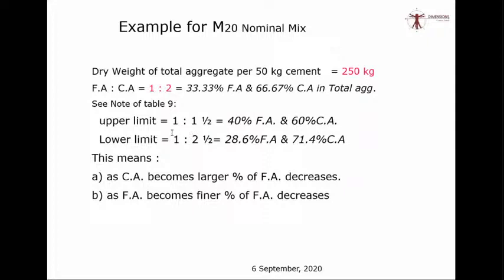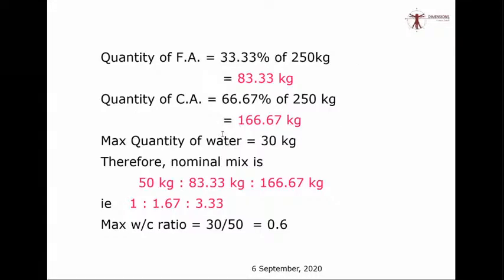See, I have taken an M20 example. The total aggregates per 50 kg of cement is 250 kg. And on a generality, if we assume that we are using 20 mm aggregate and zone 2, or it could be manufactured sand also, then the ratio between fine aggregate to coarse is 1:2, so 83.33 kg and 2 times 83.33 is 166.67 kg. So both put together, 83.33 plus 166.67 is 250 kg. So 50 kg of cement I have taken, 83.33 kg of fine aggregate I have taken, and 166.67 kg of coarse aggregate I have taken. So the actual ratio as recommended by IS 456 is 50 kg is to 83.33 is to 166.67 kg.